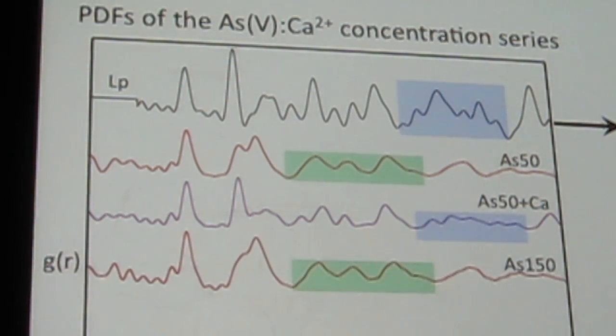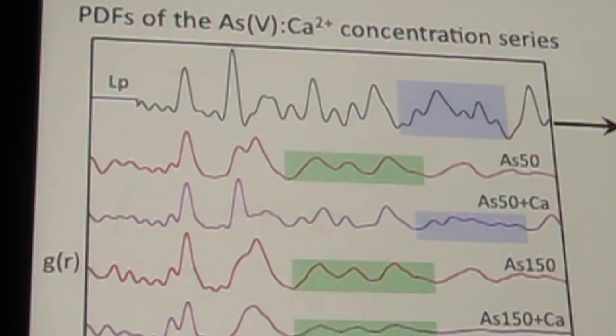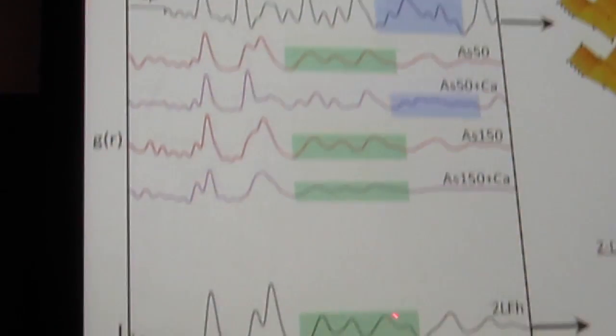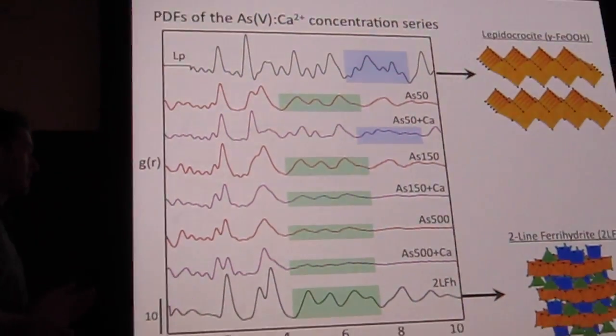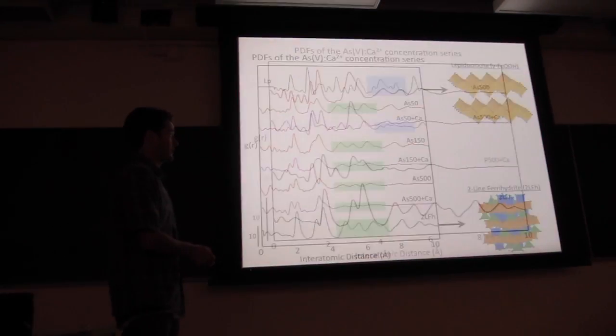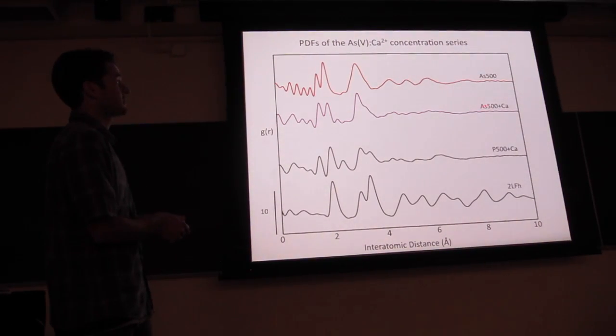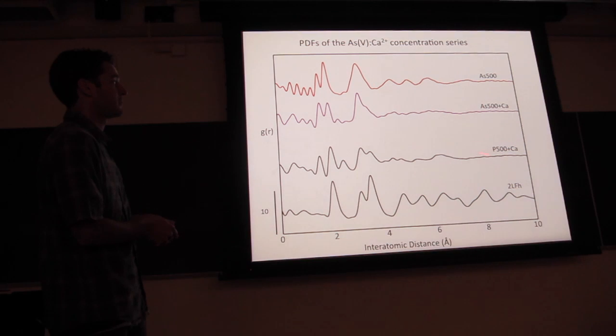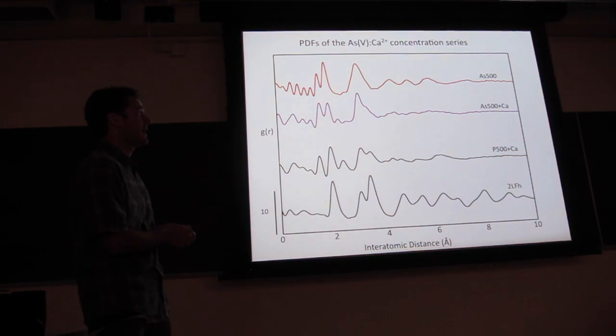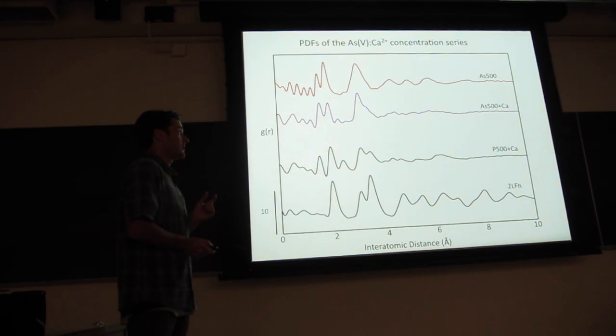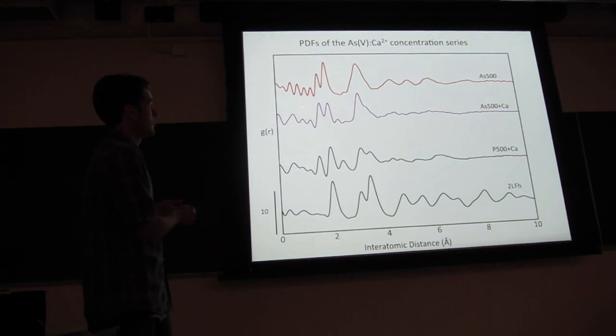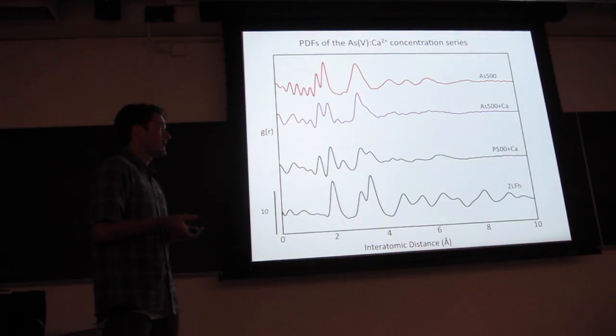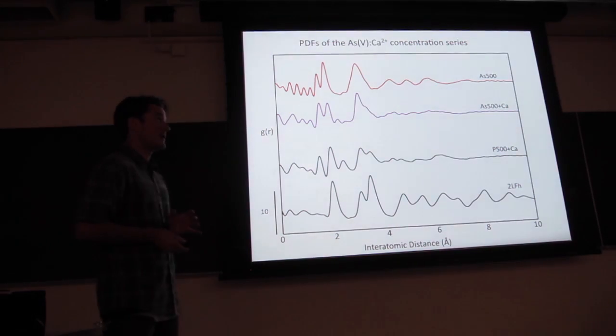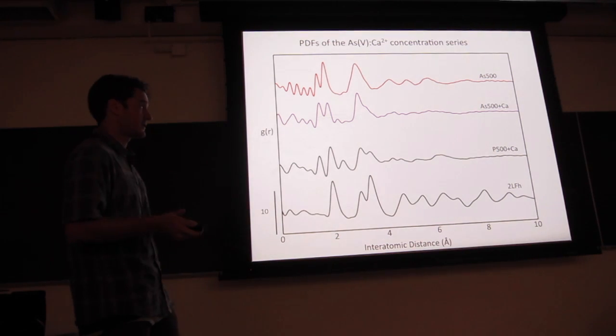At increasing arsenic concentration, both in the presence and absence of calcium, we get ferrihydrite-like material, and here are these three peaks that we see in ferrihydrite. And now at the highest arsenic concentration, these samples are actually pretty interesting, so I'm going to zoom in on these. Especially arsenic 500 plus calcium and P500 plus calcium. The peaks die out at about 7 angstroms or so. And that is incredibly small. And that means that you can only really describe these samples as polymers. And they have extremely large surface area and extremely high arsenic or phosphorus to solids ratios.